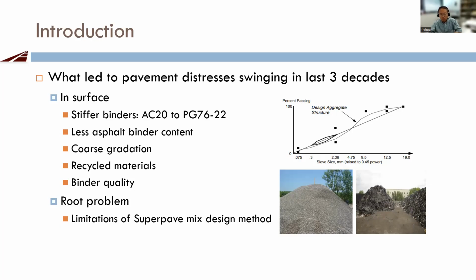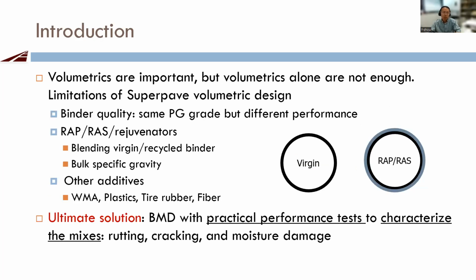And we are using lots of coarse gradation. That led to the moisture damage issue. And we have been using recycled materials in the last 10, 15 years. And another thing, potentially the binder quality. But all of these are reasons, but the root problem still is the limitations of our current Superpave mix design method. So in order to truly solve this problem, we have to look into the root problem and solve the issues from the root. So what's the problem with the current Superpave volumetric design?